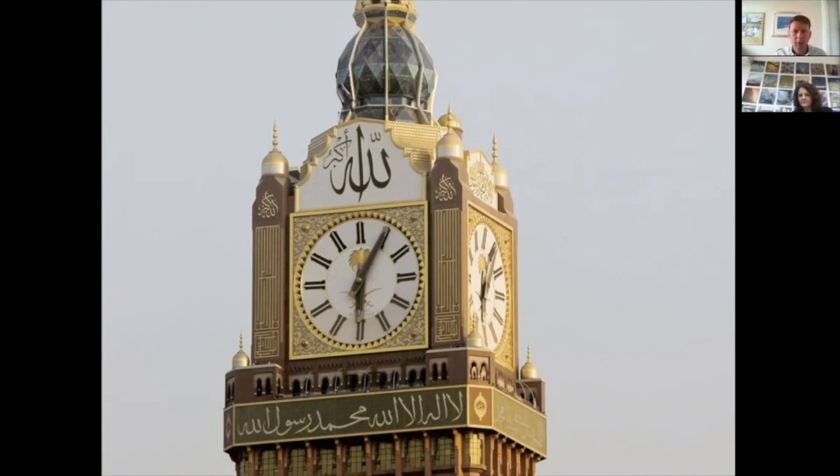As they were going through the design, they decided to add the clock, a museum, and a centre for studying astronomy on top of the building. This resulted in a big increase in the size of the building, which happened after the foundations had already been started — so there was a strict limit on how much weight could be placed up there. By making the cladding in FRP, it was at about 20 to 30 percent of the weight of a traditional GRC cladding system, which also allowed a lighter substructure and lighter main structure. It was also a complicated facade with a lot of 3D moulding in the calligraphy and decoration around the clock tower, which was easy to realise with moulded FRP composites.